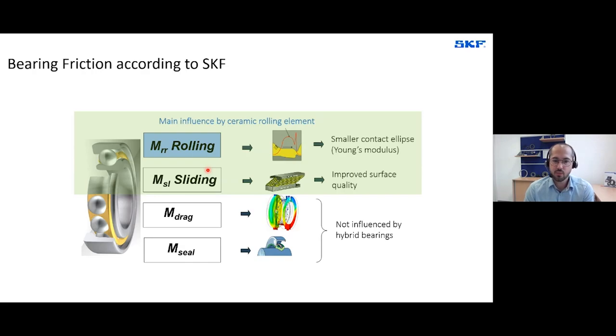What is directly influenced by hybrid bearings and by the ceramic rolling elements is the rolling friction torque and the sliding torque. Rolling losses are smaller in hybrid bearings because of the smaller contact ellipse, which is caused by a higher Young's modulus. And the sliding friction torque is reduced because of better surface quality of ceramic rolling elements.